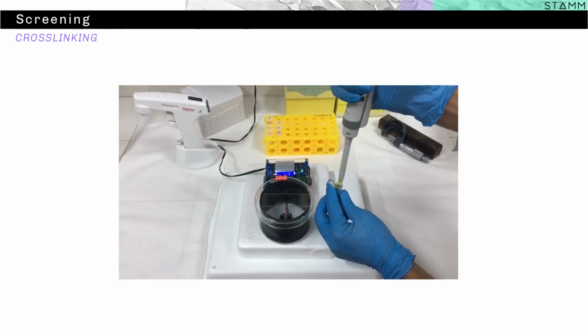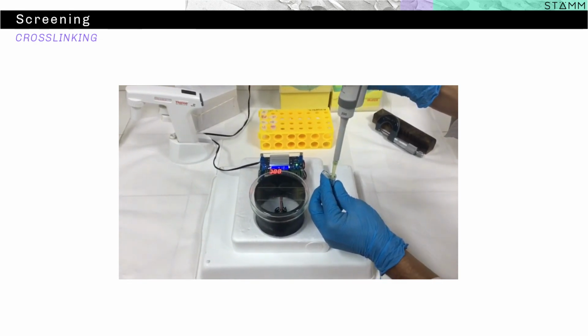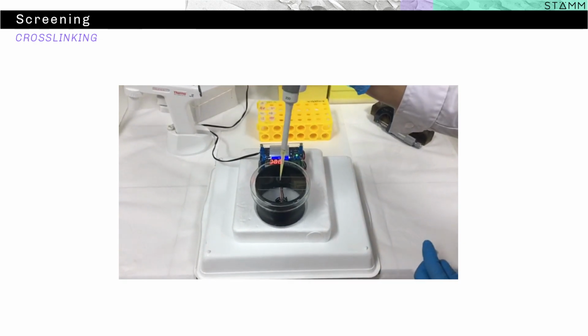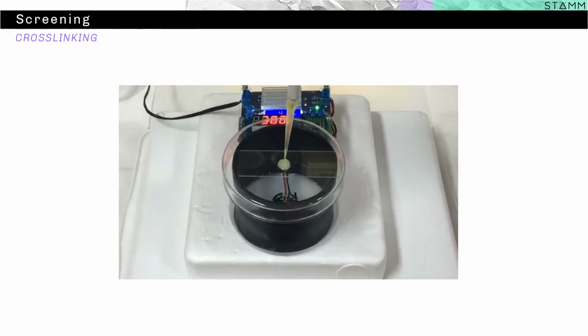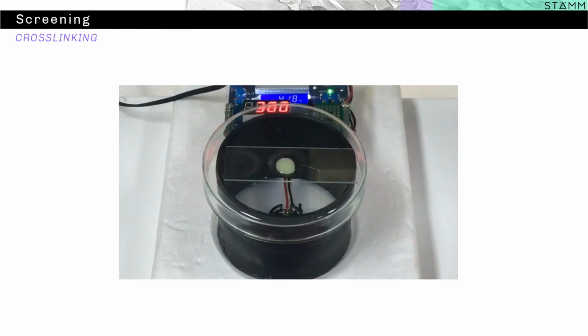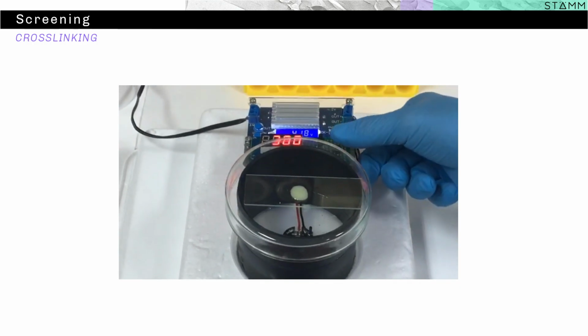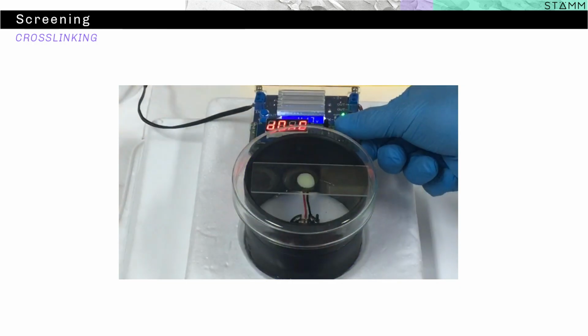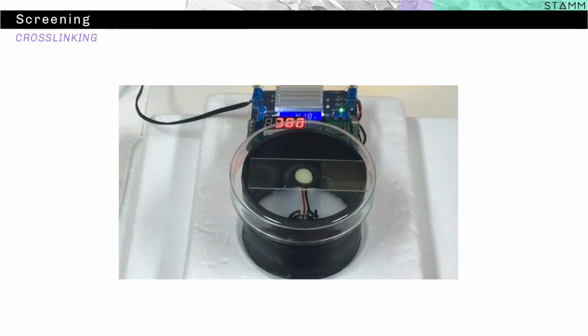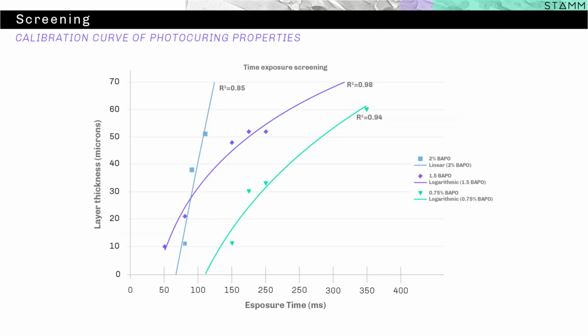Therefore, we had to carry out calibration curves for each one of these formulations, defining its ability to be light cured or not. It responds to different thresholds for photocuring, and its response curve to different times of exposure and different light outputs. To characterize the behavior of a resin in its development, a working curve analysis must be performed. The working curve is a function that relates the layer thickness that is built and the exposure time of the light engine and the potency of the light engines.